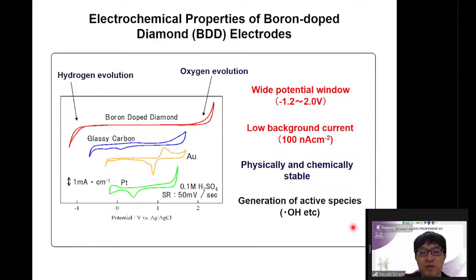Maybe this was also explained last time. The one important point is a wide potential window compared to other electrodes. Other electrodes show oxygen evolution around here and hydrogen evolution around here, but no reaction, no hydrogen evolution, no oxygen evolution, shows the potential window. But in the boron-doped diamond case, the potential window is very wide. Oxygen evolution is difficult. Hydrogen evolution is difficult.